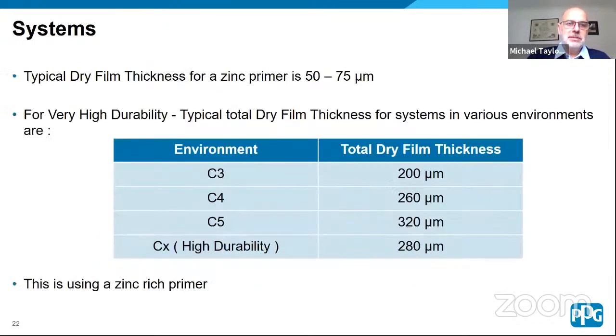So what about typical systems? As I mentioned before, the typical dry film thickness for a zinc primer is 50 to 75 microns. And for a very high durable system, so greater than 25 years, a typical total dry film thickness, this is the whole system, the various environments are listed there. So for C3, you'd be looking at 200 microns of a coating system, C4 260, and C5 320.